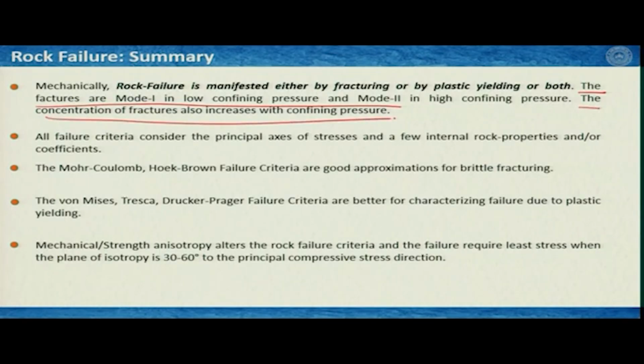All failure criteria consider the principal axes of stresses and a few internal rock properties and/or coefficients. The Mohr-Coulomb and Hoek-Brown failure criteria are good approximations for brittle fracturing, and this is what we have to consider. However, the von Mises, Tresca and other failure criteria are better for characterizing the failure due to plastic yielding. And finally, you have learnt in the last slide that mechanical strength anisotropy alters the rock failure criteria, and the failure requires least stress when the plane of anisotropy is around 30 to 60 degrees to the principal compression stress direction.